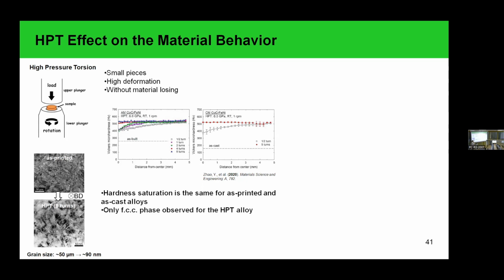Also, we investigated the effect of the intensive deformation process on the material behavior, and for this purpose we used high-pressure torsion. This technique provides the possibility to use small pieces of material. We can achieve a high deformation without losing material, and the result of this part of the work can demonstrate how the properties of our additive manufacturing materials can be improved with these grain refinement techniques, and also consider further application of our additive material in harsh environments.